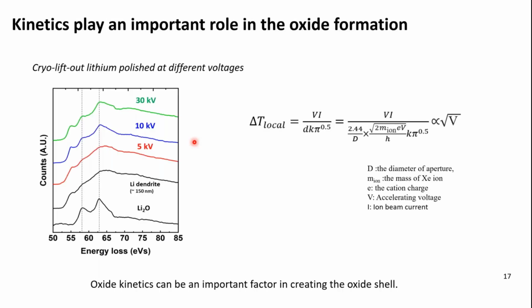Okay, we talk about thermodynamics, and we talk about the lithium oxide diffraction patterns even existing in the thick samples. And we also noticed that the accelerating voltage plays an important role in the oxidation. So as you can see in the graph on the left, when we use 5 kV ion beam voltage, the oxidation is extremely suppressed. And I believe the beam-induced local heating can accelerate the kinetics of the oxide formation, such that you can see the thicker oxide shell along the beam axis.